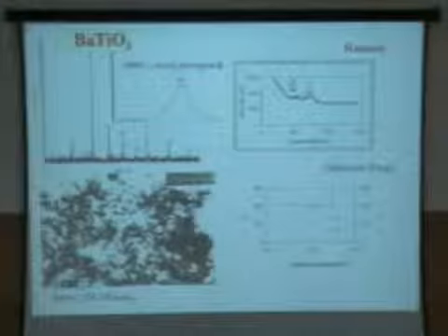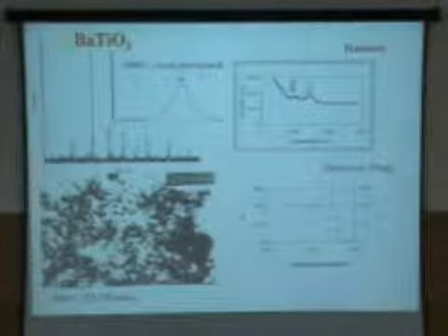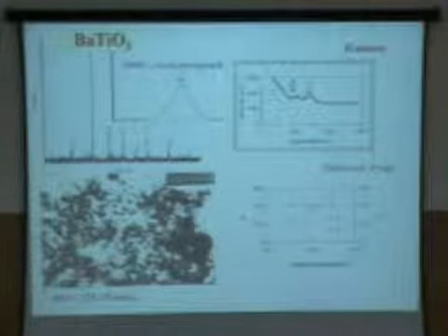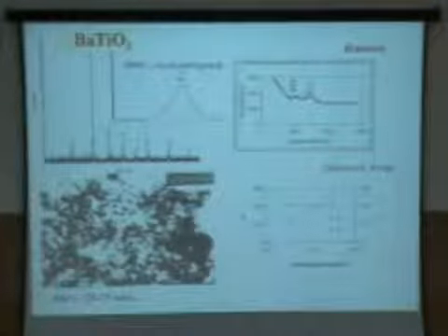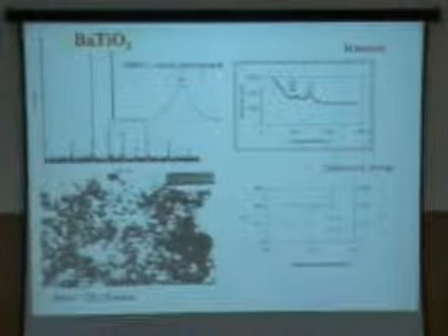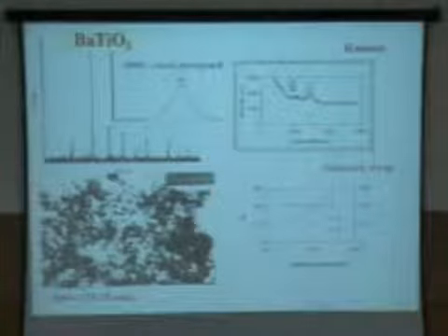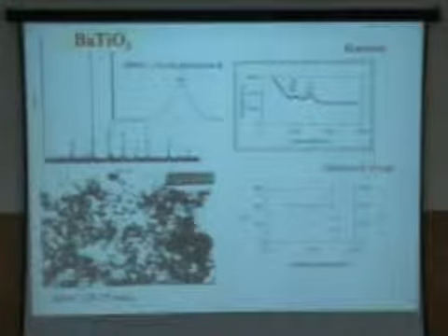Normally, ferroelectricity decreases as the particle size decreases. So you lose the ordered moment, and there are a lot of theories at what size it should disappear. We showed that at 20 nanometers we can still see ferroelectricity. Of course, the dielectric constant goes down dramatically.